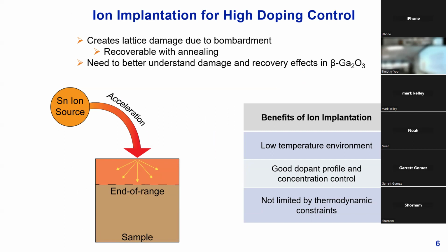So in ion implantation, you have your ion source. When those ions are excited, they're strongly accelerated through an electric field, where they hit the surface of your sample and bombard your lattice, and it cascades through up to a certain point called the end of range. This dopant profiling and concentration control is really good in ion implantation, as well as having other benefits like operating in a low temperature environment, as well as not being limited by thermodynamic constraints when you're doping.